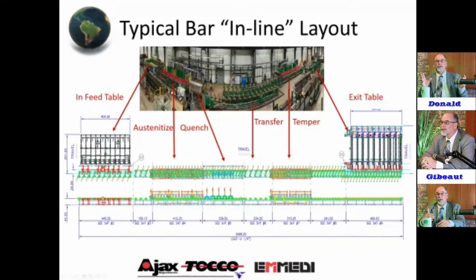And then the quench system. And as you can see, everything is driven through here for precise control through the handling. It's critical. And typically we're on 5-foot centers. It depends on your length and your size of tubing for the proper support. Because as you get up in these high temperatures, especially above the magnetic Curie, the plasticity of the tube gets higher. So you have to support it very well to keep it straight and keep it from distorting.